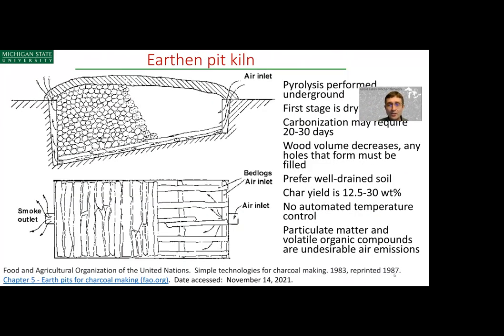Now, it turns out it's actually quite easy to perform pyrolysis. Here is an example of an earthen pit kiln. You can see that we let air in on the far right-hand side. Air comes in, and this is a small amount of air—not enough to completely combust all the feedstock buried in this earthen pit kiln. What that does is combust a small fraction of that feedstock.